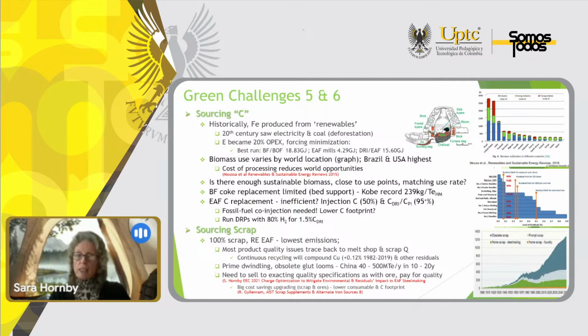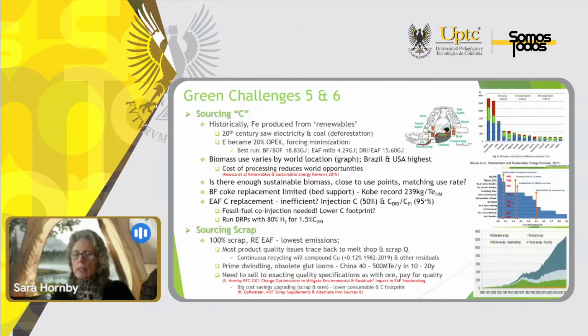The other issue, number 6, is sourcing scrap. 100% scrap renewable energy electric arc furnaces have the lowest emissions, no question. Most of the product quality is traced back to the melt shop and the quality of the scrap. And you can see from the right-hand side bottom that the obsolete scrap, the dark blue, is going to increase significantly to 2050. And with continuous recycling, the issue with the residuals, the copper especially, is going to increase significantly. The prime scrap is dwindling.